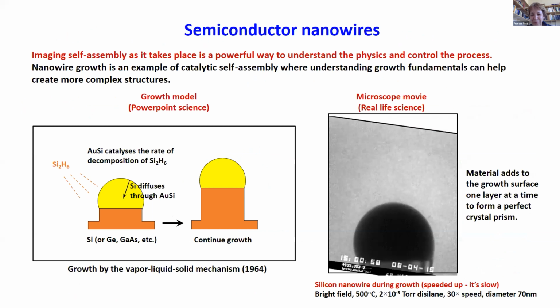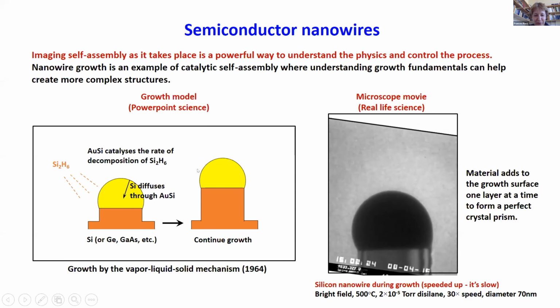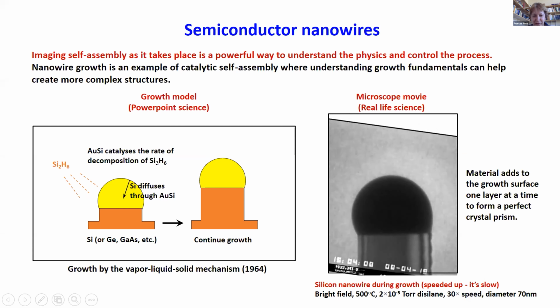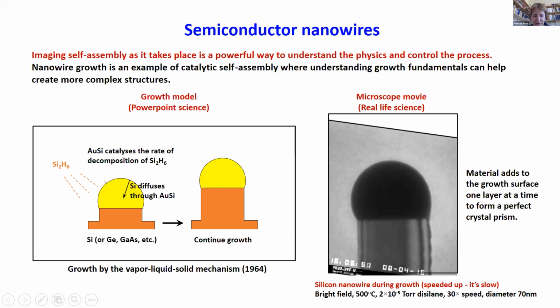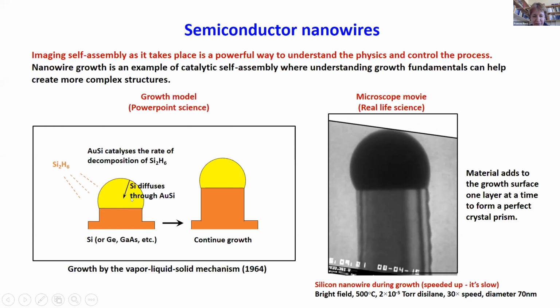So talking about nanoscale processes that you can trigger in the electron microscope, we're naturally drawn towards nanowires because the process of forming nanowires was of great interest in microelectronics because it's a way to create small structures without using lithography. So the process works like is shown in this PowerPoint science slide. So we get a lot of this with nanoscience because often you don't have the image that goes with. So as you add your material, in this case silicon supplied as disilane, it lands on the surface of the sample. The sample is covered by droplets of gold silicon eutectic. You'll recognize that from the first slide.